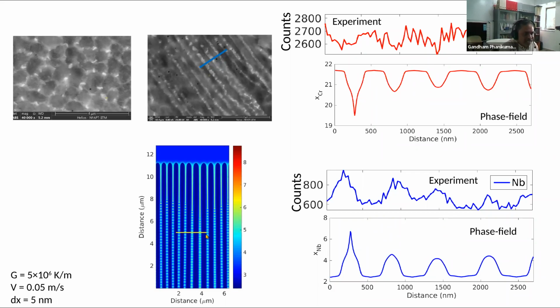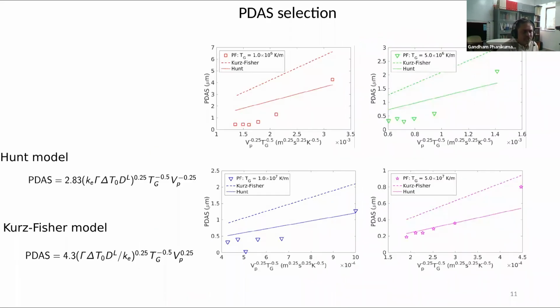Okay, so this microstructural variation is something that we can simulate and therefore also control, because we can always simulate for conditions and then go on to print it such that we have the segregations as we want. Okay, now what is the use of doing this? The advantage of doing simulations is that you can actually go on to find out whether we can calibrate some of the known models of the spacings of the printed microstructures. So the spacings are lower means higher strength. Okay, so some such correlations we can calibrate, and thereby we can actually predict what is the way the spacings are changing when you change the process condition.